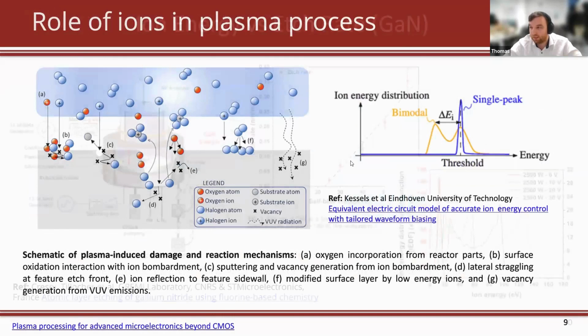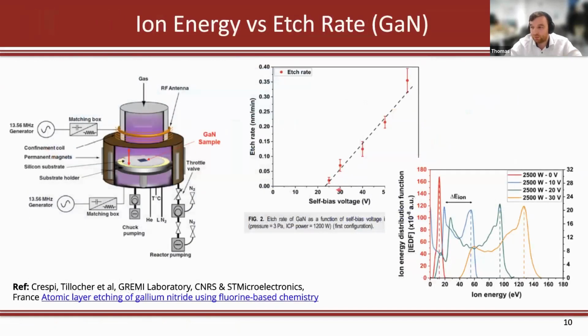So let me go ahead a little bit, just to show you some real examples, okay? This is from a nice paper from Gremy, where they were measuring the etch rate as a function of the bias applied to the electrode. This sort of data exists for a lot of materials out there. So here are etch rates in nanometers per minute and the bias voltage. Now, bias voltage is not exactly the ion energy because you have the plasma potential, but it's basically ion energy.